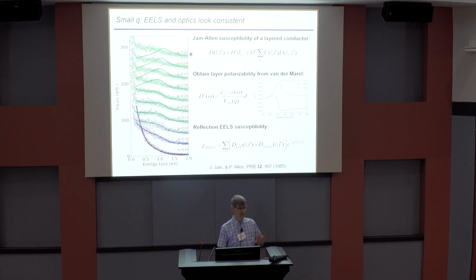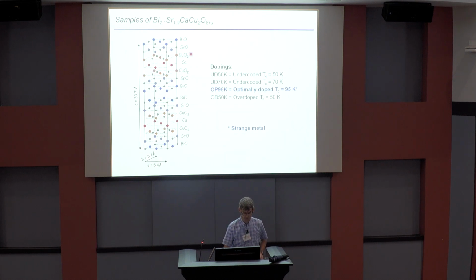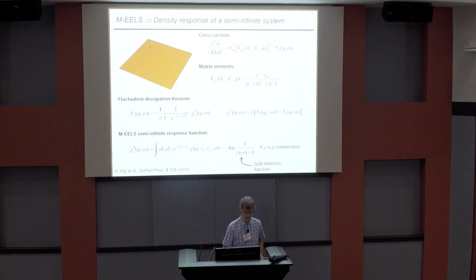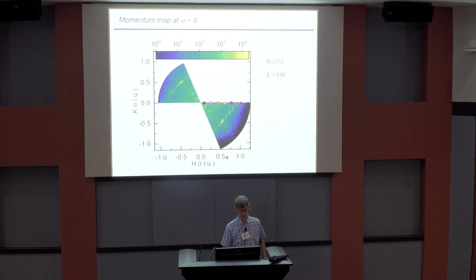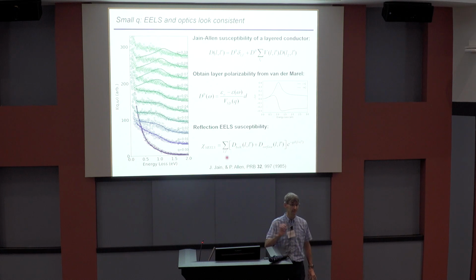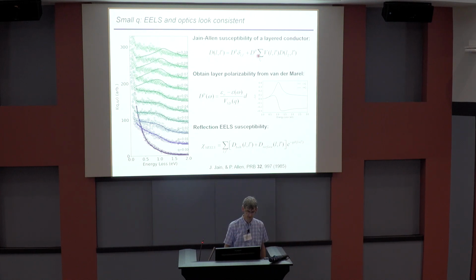Now EELS measures this funny response function that I showed you earlier, and if I had a really polished talk, I would have emphasized it more. So this is the response function we measure with EELS. It's not exactly the same as the response function you measure with optics, but we can relate them. We can do that by using a framework developed by Jain and Allen in the 1980s. This was actually for analyzing Raman scattering from gallium arsenide heterostructures. There's a lot of history behind that, but basically D naught is the response measured with optics.